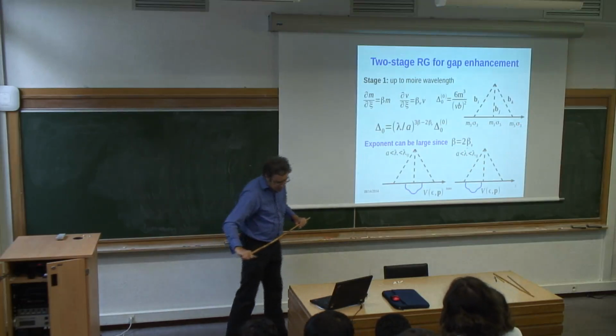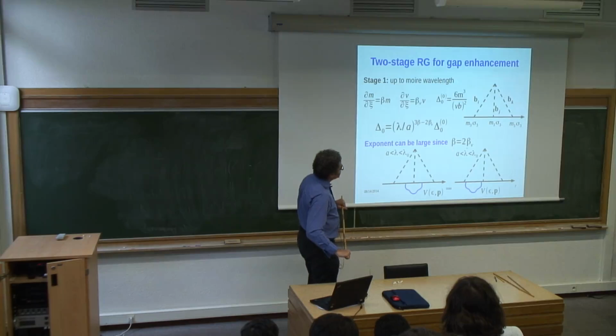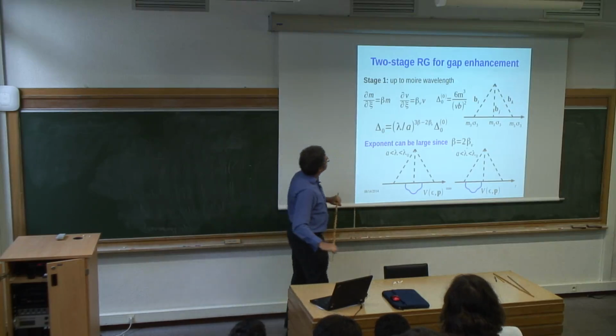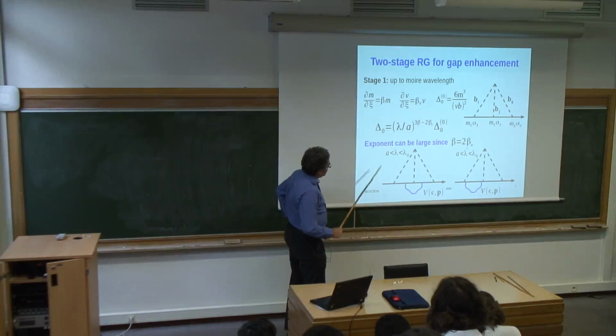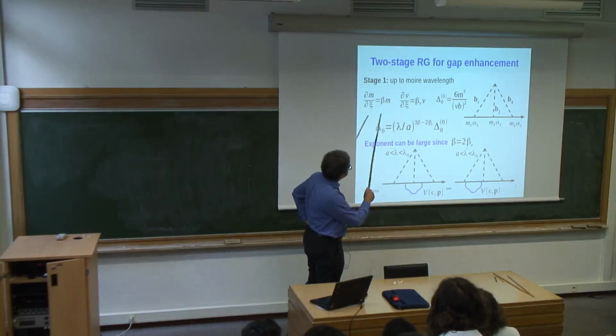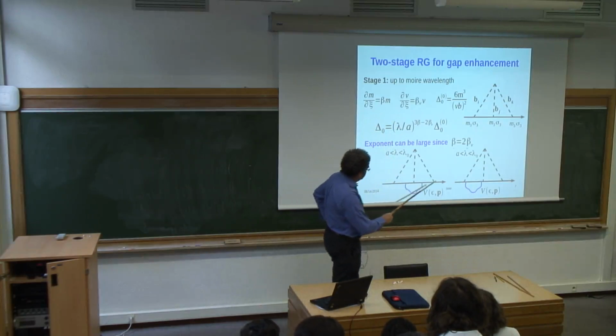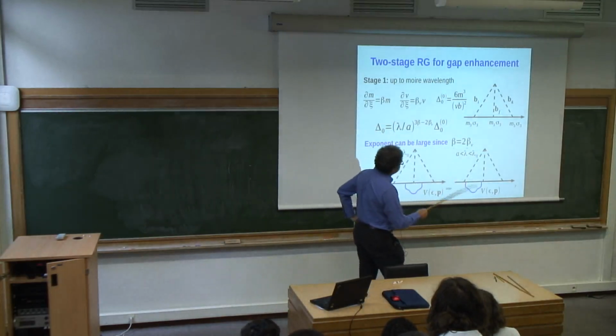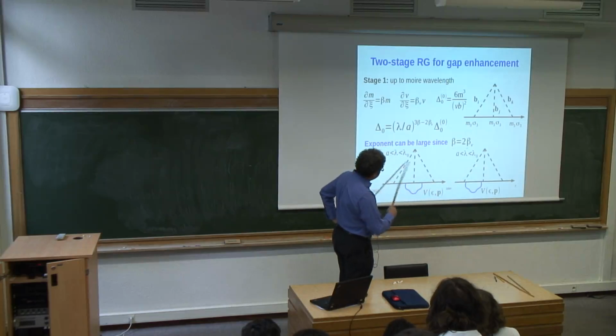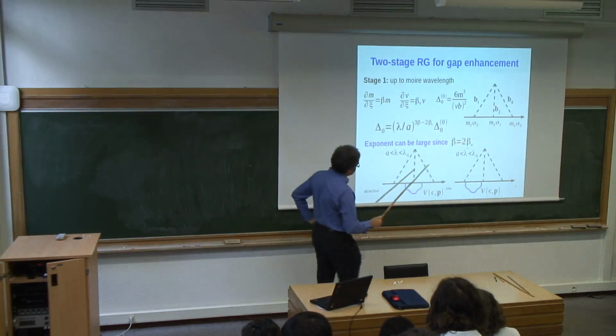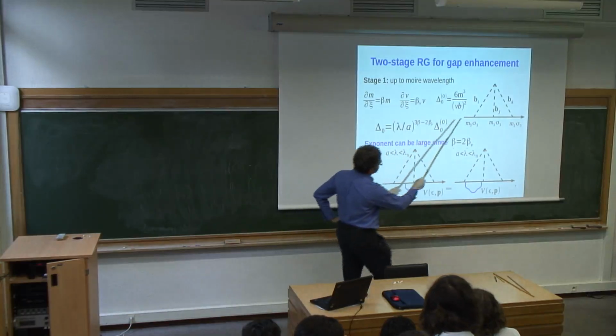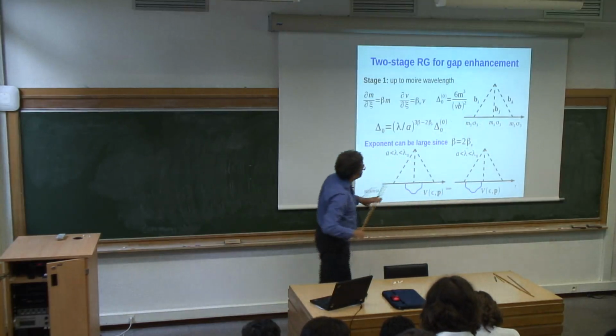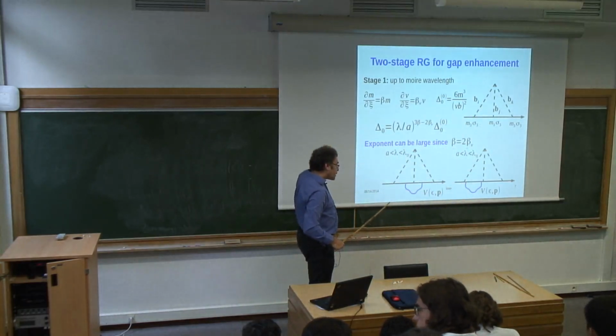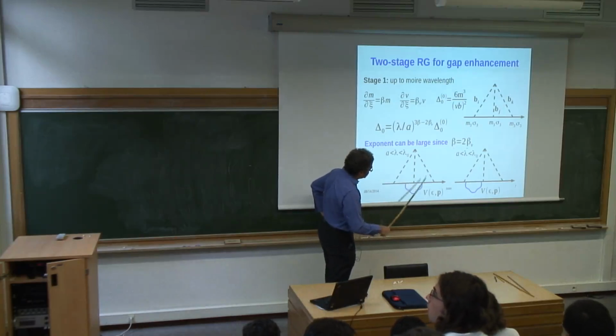interactions might be useful to consider to explain this discrepancy. And so the way renormalization proceeds is that you consider vertex corrections to each vertex of this third order diagram that opens a gap. It's a self-energy insertion in the Green's function, single particle self-energy insertion in the Green's function for non-interacting electrons, Bragg scattering on the spatially dependent mass term, and then that we have to renormalize by adding interactions, and so these vertex corrections will generate